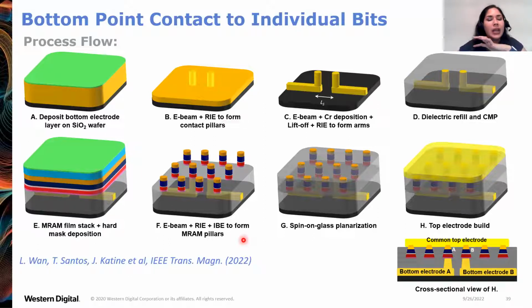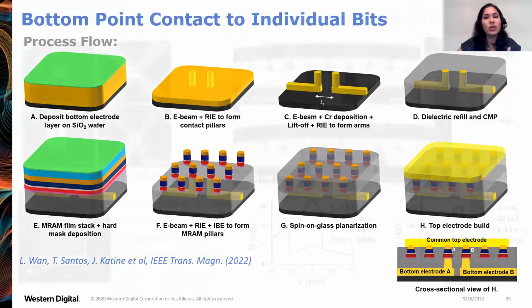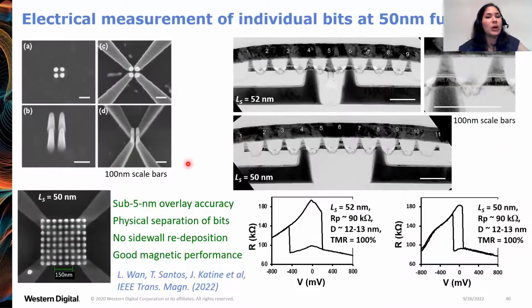Then we make the MRAM pillar array using the process I described previously. We do a spin on glass for planarization, and then a common top electrode over the array, so that at cross section, this is what we expect here, but I can show you in our real images what we ended up with.